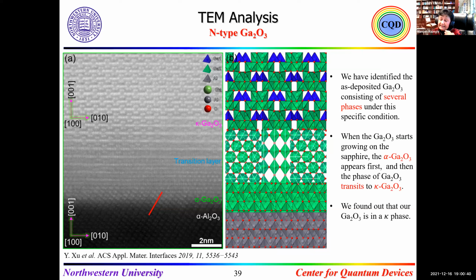So that is the reason at this time I cannot tell you exactly the number of the defect, because we are far from that. And all of the devices that we demonstrated, the defect density has to be at least 10 to the 8 to 10 to the 9, similar to aluminum nitride gallium nitride when you put on sapphire. But the beauty is, as it's wide band gap material, that is one of the big problems at this time.